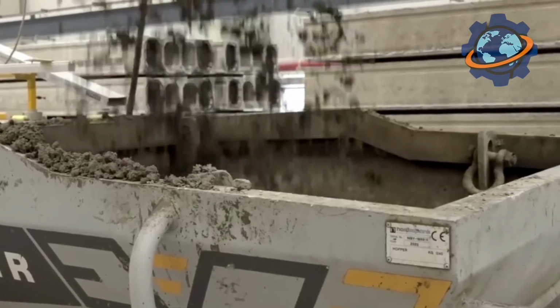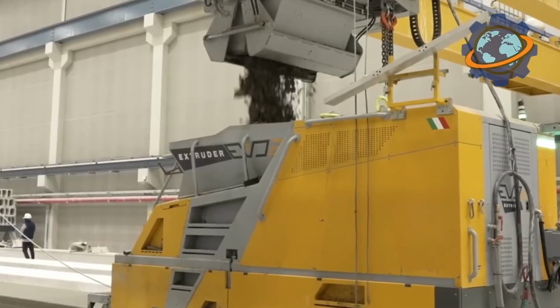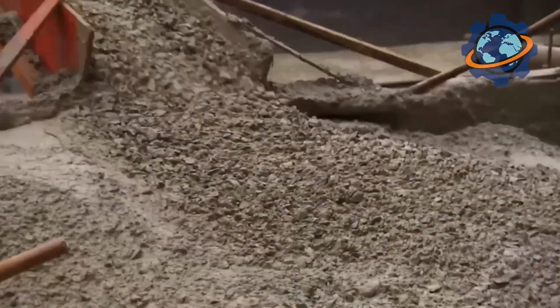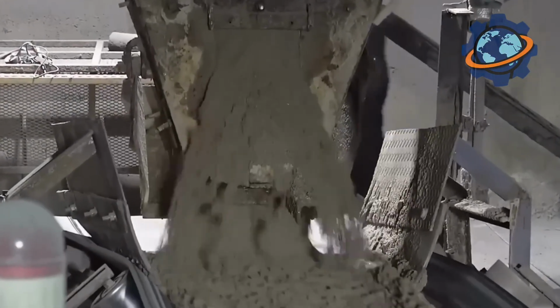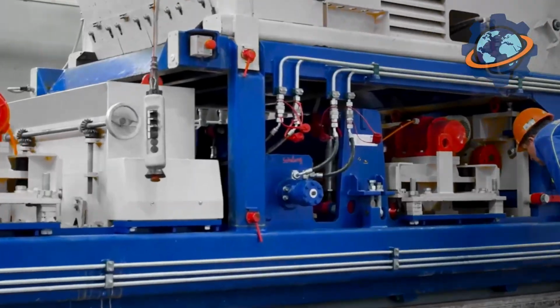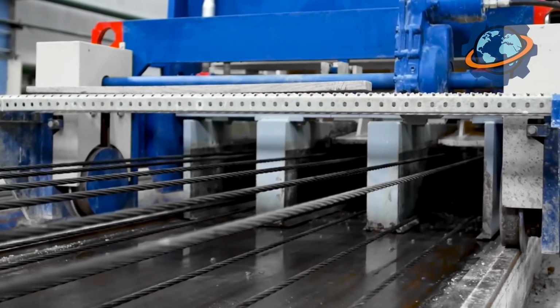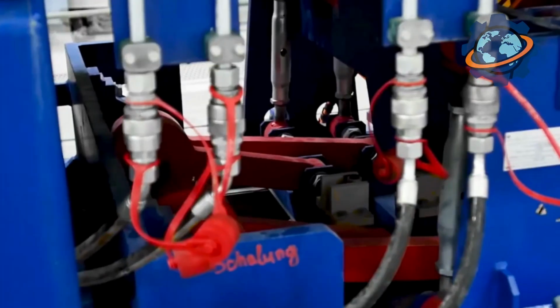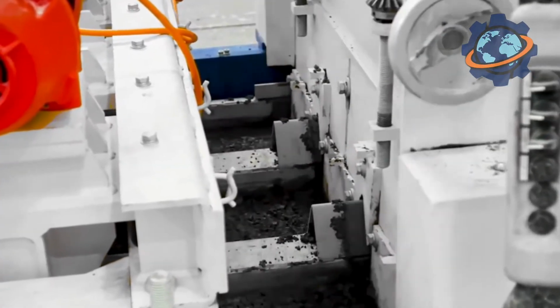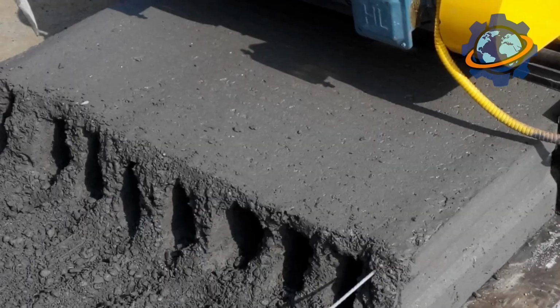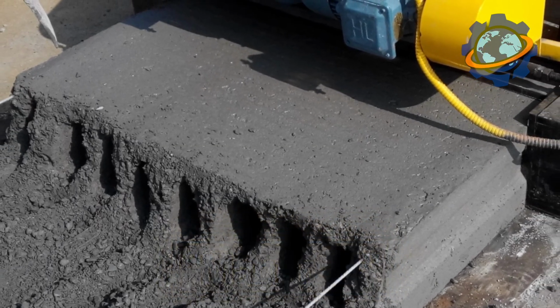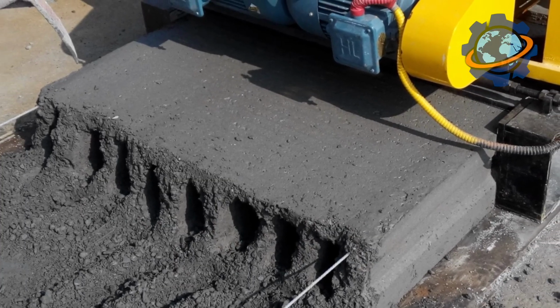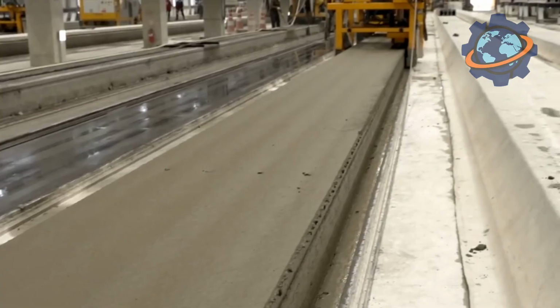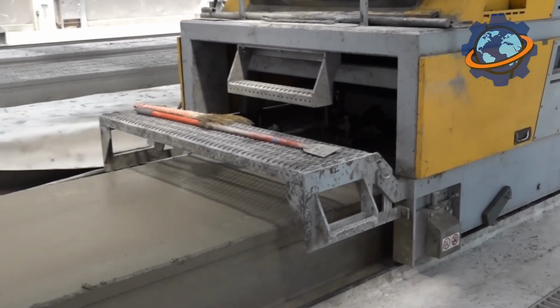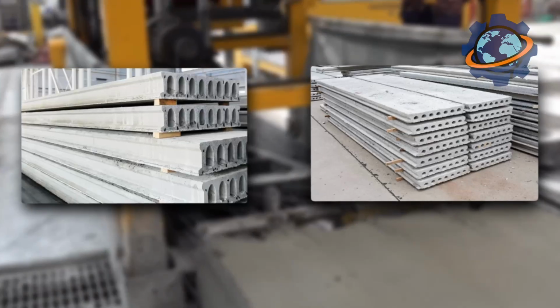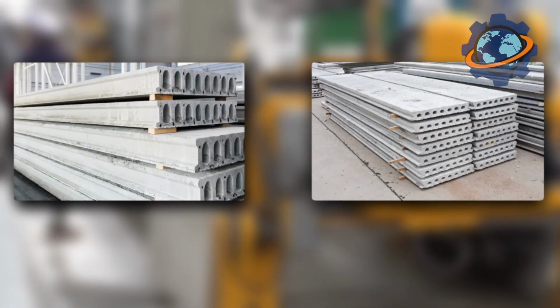Firstly, the concrete from the hopper is fed downwards, enveloping our tensioned steel strands. Secondly, special vibrators and compactors ram this dry mix with incredible force, making it unbelievably dense. And thirdly, and most importantly, inside the machine are special forming tubes, or mandrels, which vibrate as they push through the concrete, leaving behind perfectly round, smooth voids. The machine, like a giant concrete snail, slowly crawls forward, leaving in its wake a perfectly formed, endless concrete slab with hollow cores inside and tensioned steel muscles hidden within its body.